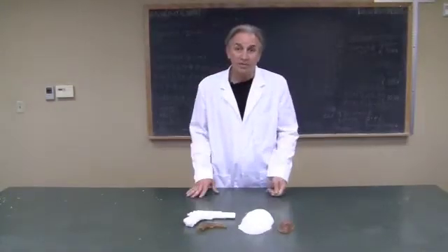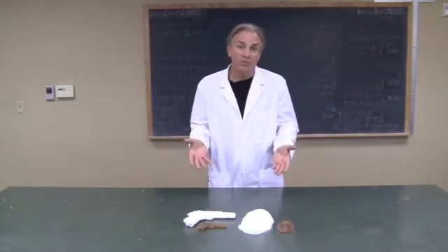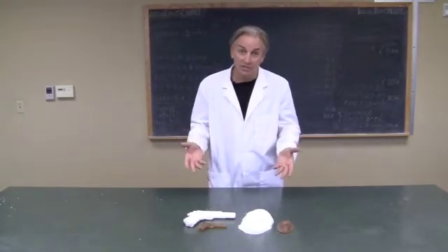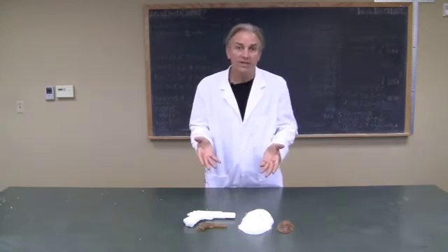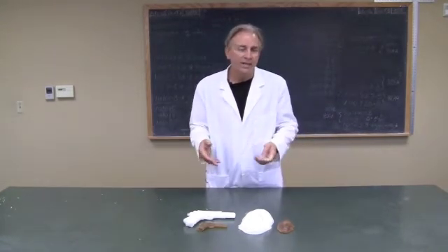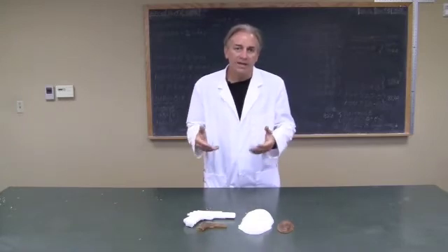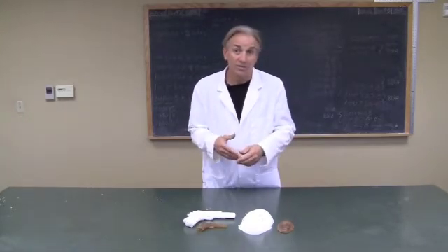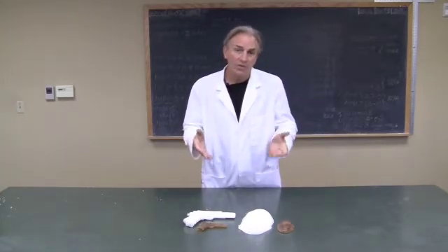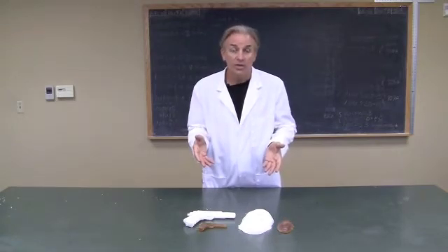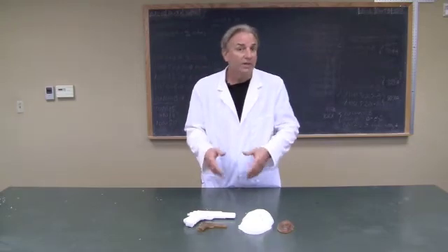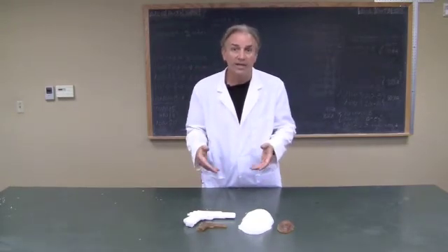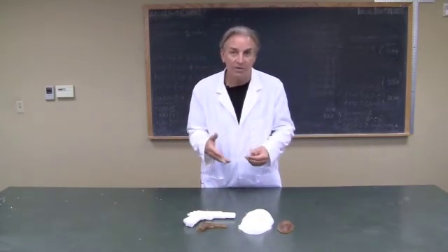We've made the parts, but we want to tell you a few things about HydroSpan 400. It's a great product, but there are some limitations. Whenever you do the parts, you want to let them dehydrate themselves in an air-conditioned environment. It's not good to force them in an oven—an oven will actually reverse the polymer in some cases. A food dehydrator would work as well, but if you do it too fast, you might get some surface cracking. So the best thing to do is let them dehydrate on their own in a dry, air-conditioned environment over time.